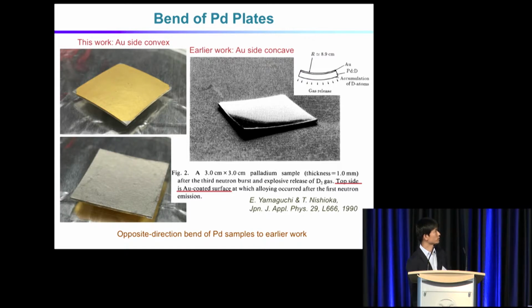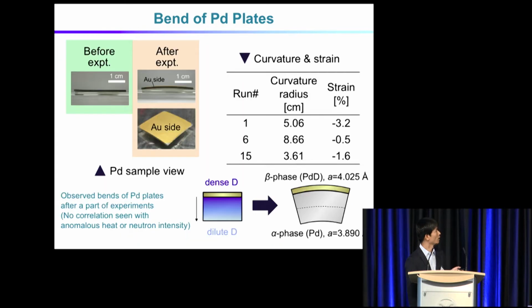And then we also observed a bend of the plate, which was in the opposite direction to Yamaguchi's experiment 20 or 30 years ago, for which we don't know the reason. And then we investigated the curvature in relation to the phase changes, beta and alpha phase. And we found that the curvature was probably in good agreement with the difference of the lattice constant between the alpha and beta phases, as I will show you later.